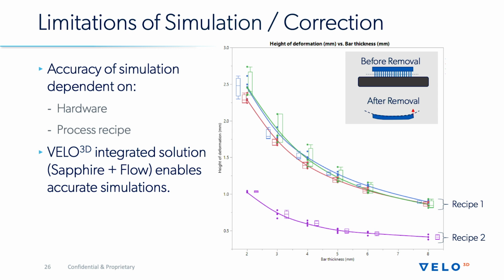Now, if you use one of the recipes that we've developed and you run it across multiple different machines, you end up with the blue, red, and green curves here, where you get very consistent deformation as you print the same objects. But if you change and you use an alternative recipe that we've also developed and print the exact same structure, what you end up getting is the purple curve. And so the deformation is changed by a factor of 2.5, even though it's the exact same material, exact same geometry. And so for these simulations to be accurate, it needs to come with an integrated approach where it's considering the hardware, the process, and the software at the same time. And that's where Velo's integrated solution enables accurate simulations, because we're providing all of those at the same time. And so we can carefully calibrate the models to give the right predictions for the processes that are run on the machine.